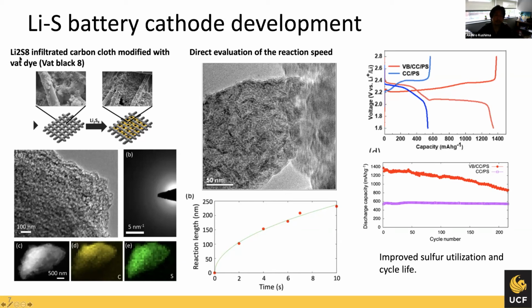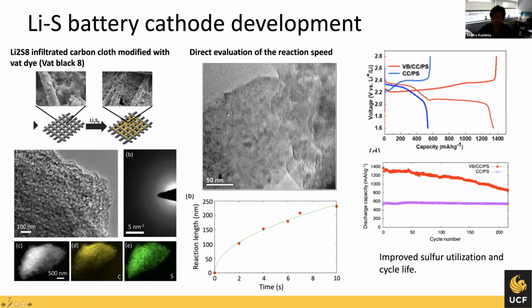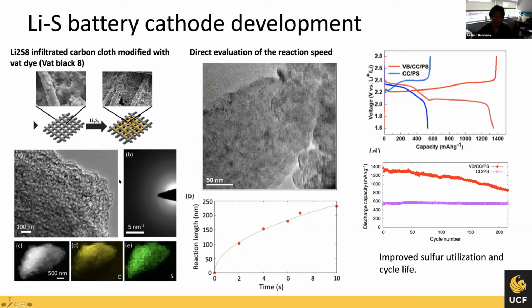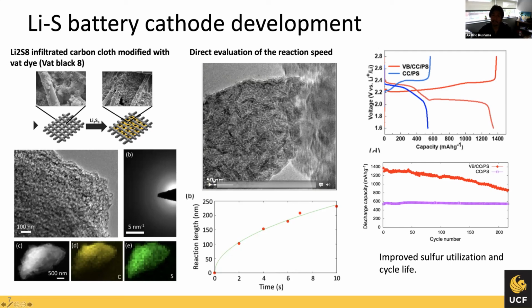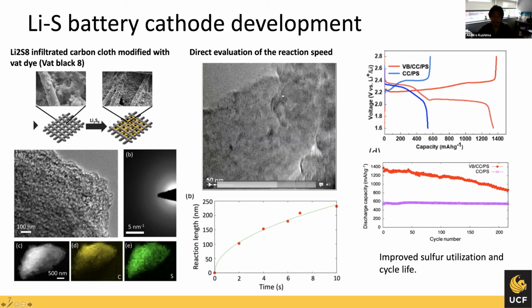Then later you infiltrate lithium polysulfide into it, and they will create nanoporous structures that confine the lithium polysulfide. You can see from this TEM image, the sulfur is uniformly distributed in these pores, which are about 5 nanometers in size. And you can use this in the in-situ microscope and directly observe how this reaction takes place in this kind of environment. The reaction takes place really quickly across these materials, and you can see there is not much volume change, which is good for enhancing the cycle lifetime.